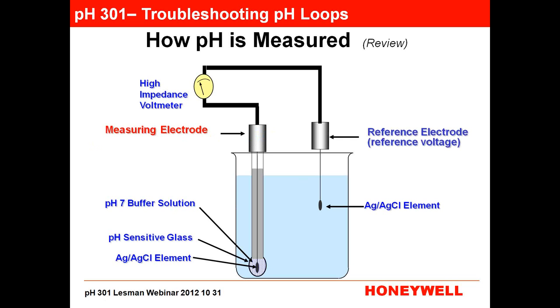The problem is you can't just put it in the process bare like that, because it would, A, not have a constant voltage to compare to, and, B, it would probably be damaged by your process fluid. So we put it in a fluid or a gel of potassium chloride, and that potassium chloride is an electrolyte, so it carries current very readily, and it fixes the voltage at the reference electrode. And that's great, but now you're not connected to the process. You're separated from the process, so you don't have a complete circuit.